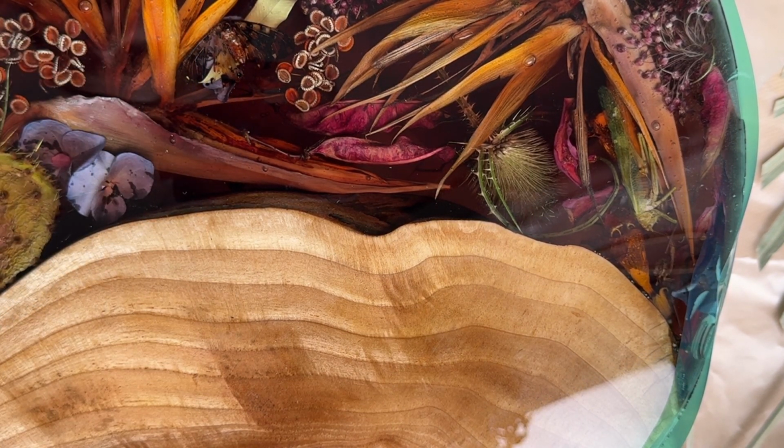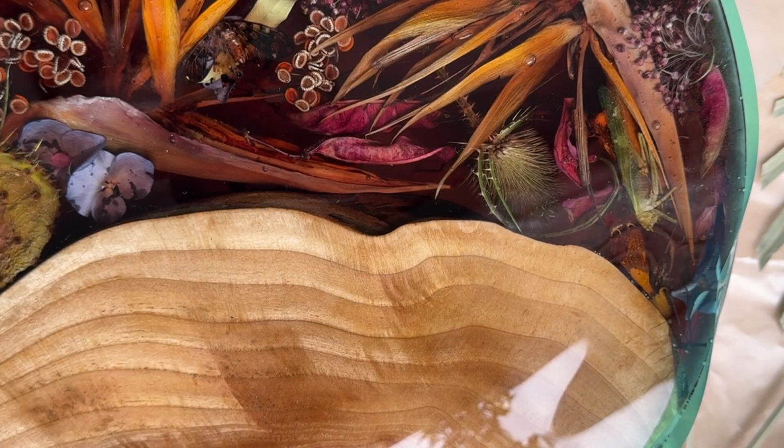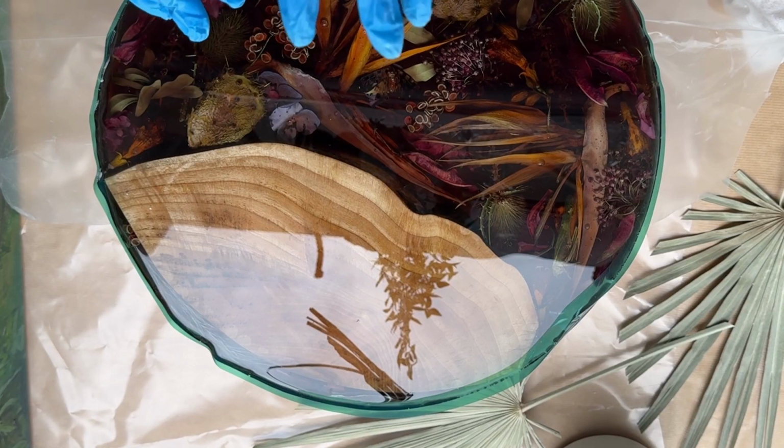Let me remind you again, guys. I have resin for volumetric fillings. I added a little more hardener to it. It's a trick. And thus, my resin will harden faster than 2 days, but it will certainly take a day to harden, and it will begin to thicken and polymerize after about 3 to 4 hours. But to conduct such experiments, you must also experiment beforehand. So please, before accelerating your resin like this, you must understand it, know its lifespan, know how long it will take to harden before you can do tricks with it.